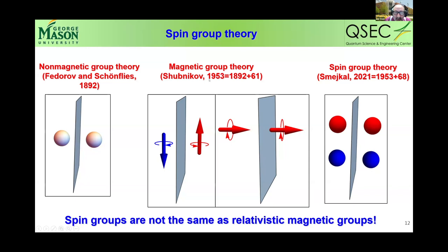And that was enormously more complicated, for the reason that spin, generally speaking, is not the same object as charge. It's a pseudovector, and that means that if you consider, for instance, a symmetry element, let's say a mirror, then the way spin responds to these symmetry operations depends on how the spin is directed. If it's parallel to the mirror plane, you can see that very easily, because spin has the same property as a circular current loop, so this spin flips direction, or if it's perpendicular, it does not. And that results in enormous complications. Basically, the magnetic group, even for collinear materials, depends on the direction of the spin, and there are thousands of them now.